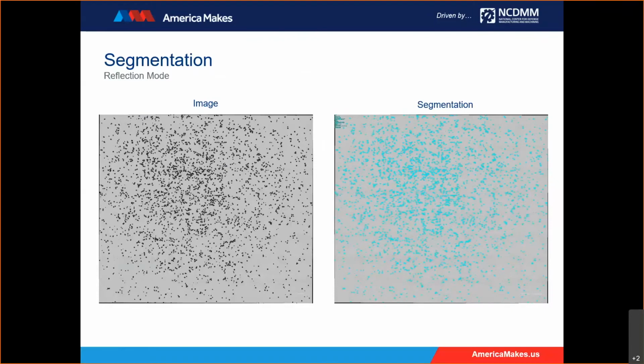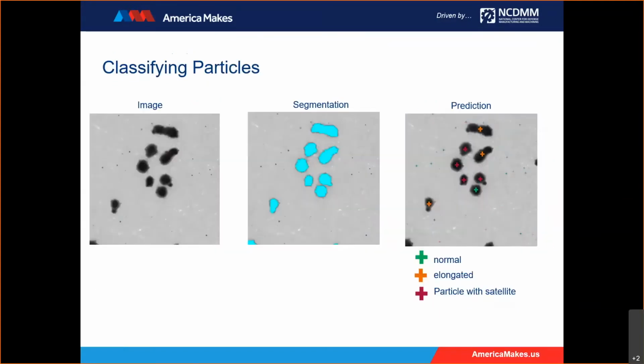So we're measuring particle roughness in this way in our light microscopy workflow. At first, we collect a mosaic, like I said earlier, like the image on the left here with 7,000 particles. Then we can segment the particles from the background, as you can see on the right, and calculate the features of each particle, including the particle roughness. We can use those features to train a machine learning model to make a prediction for particle classification. So we go from the imaging to some segmentation to a prediction.